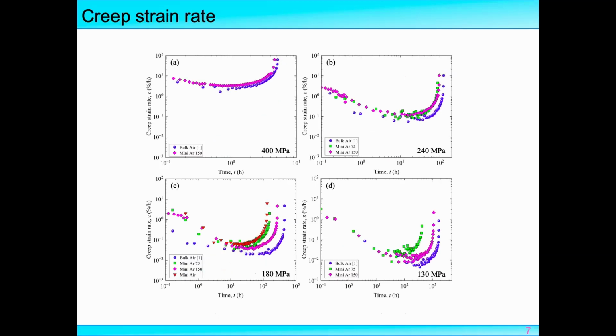Another one is the creep strain rate. From this figure, we can also obtain some similar conclusion, which is that the minimum strain rate for standard specimen is the lowest among those test series, and the test in low air flow is higher. The test result in the low air flow has a much higher minimum creep strain rate.